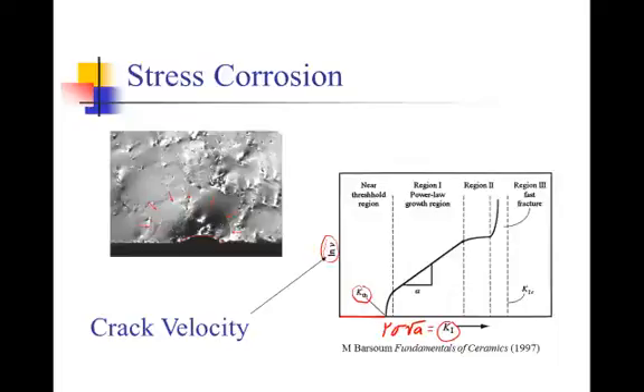After we pass that point, which is unfortunately a very low stress intensity factor for most ceramics, so we tend to always be passing that point, then we start to get some crack growth occurring. And as the crack grows larger, A increases, and when A increases, that causes the stress intensity factor to increase. And when the stress intensity factor increases, the graph shows that the velocity of crack growth increases. And so this is a vicious cycle, which causes the crack to not only grow, but its growth causes it to grow faster in future time.